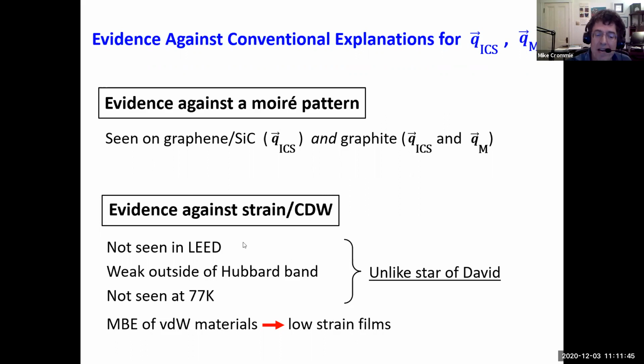Also, there's a strong energy dependence. We see these patterns at the Hubbard band, but as you move away from the Hubbard band, they die off quickly. Whereas the Star of David, we see strongly at every energy. So for a structural modification, you expect not to have a strong energy dependence. Also, we did experiments at a slightly higher temperature, 77 Kelvin, and the QICs went away. Whereas the Star of David is still there, and the difference in strain between 5 Kelvin and 77 Kelvin is not so strong. So if it's a strain effect, you would expect it to still be there, but it disappeared. So that argues against a strain origin. Also, MBE of van der Waals materials tend to be very low strain systems in general. So this is, in our opinion, very strong evidence against a conventional strain CDW explanation.